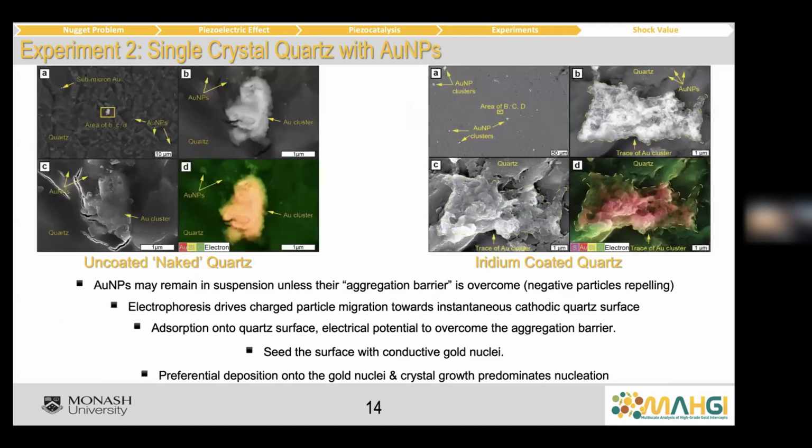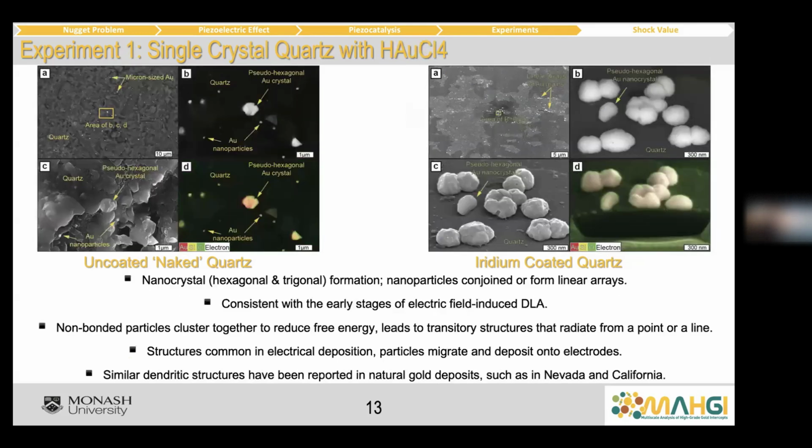And then for the nanoparticle solutions, the ones where we started with nanoparticles. Oh yeah, just an interesting thing here. When I was working with these chloride solutions, I couldn't help but make nanoparticles. It happened almost every time. I thought for the first while that I had a contamination issue or something, so I reran it a bunch, and almost every time it would happen, and you could see it happen. I had a yellow solution, and I'd be deforming it with the linear actuator. You could see it go from yellow, to kind of milky white, and then to purple. You could see it happen in a minute and a half. It was really, really cool.